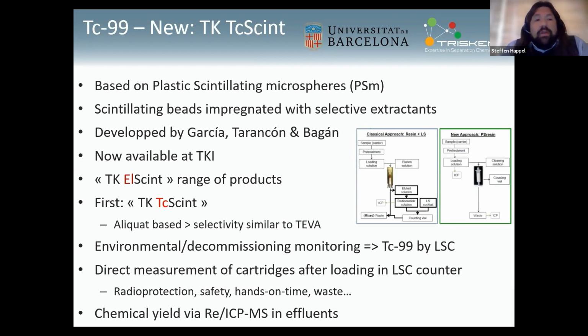We feel that there are very nice applications in environmental monitoring, but especially also in decommissioning, high active samples, where the fact that you're not eluting, not evaporating, not taking aliquots and preparing them for the measurement is quite an advantage. So just separate, keep it on the cartridge, then put the cartridge in the counter and measure directly. That we feel is a really important advantage. And as already indicated, you can use rhenium here too to determine the chemical yield, in that case via ICP-MS, by determining its concentration in the effluents. So that is something quite new and that is coming up right now.